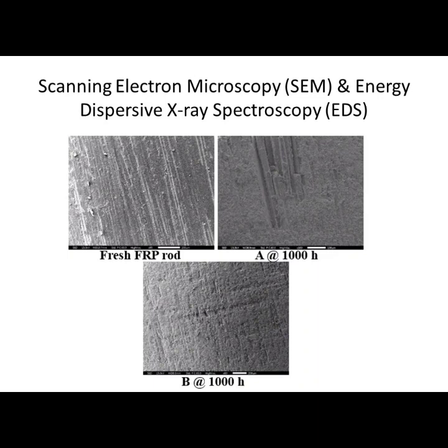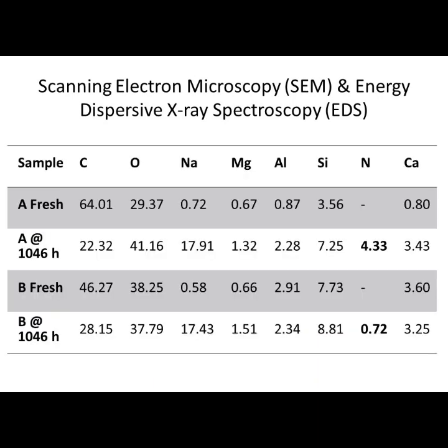However, the newly developed tracking resistant FRP rod shows a superior performance and less degradation, where the glass fiber is still covered with the epoxy resin, with slightly more rough texture in the epoxy resin. So this table now shows the atomic elemental composition on the surface of the FRP rod samples, both fresh and aged. As we see here in the normal FRP rod sample, a significant decrease in the carbon content is seen, and a significant increase in the oxygen content also is seen, which could be due to the oxidation process taking place under the impact of the electrical discharge, leading to the decomposition of the epoxy resin into water and carbon dioxide, and leading to this significant decrement in the carbon content.